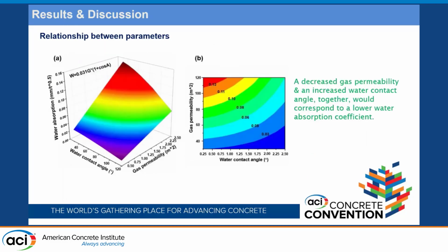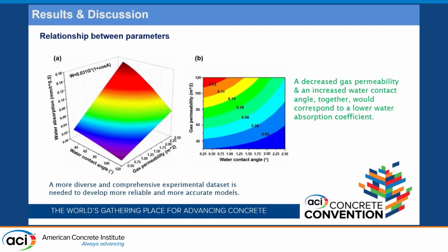Based on the data, here we propose a relationship between the water absorption coefficient, water contact angles, and the gas permeability coefficient. The result indicated that a decreased gas permeability and an increased water contact angle together will lead to a lower water absorption coefficient, and then lead to a better salt scaling resistance.